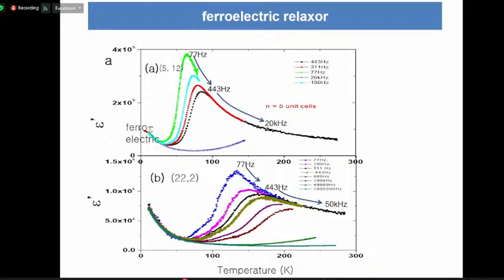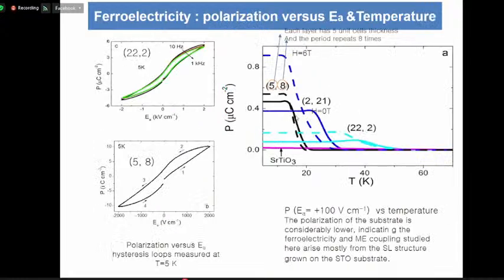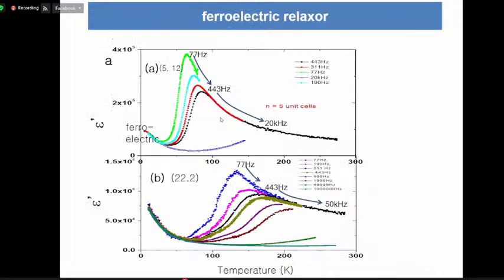This temperature is almost the same as the transition temperature of each thin film. In the 22 case it is around 40 Kelvin or something around that, and then 5 unit cells is lower than 20 Kelvin like this. The frequency dependence says the material has some time dependence, like spin glasses. This one also has some time dependence. So we call it a ferroelectric relaxor.